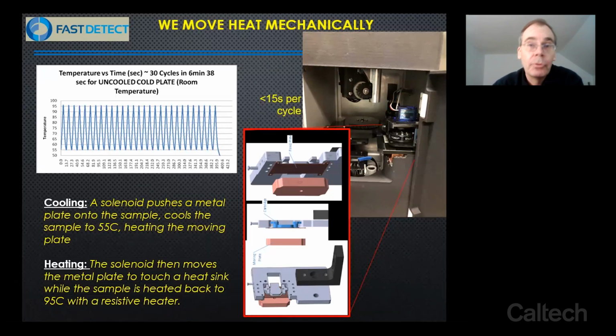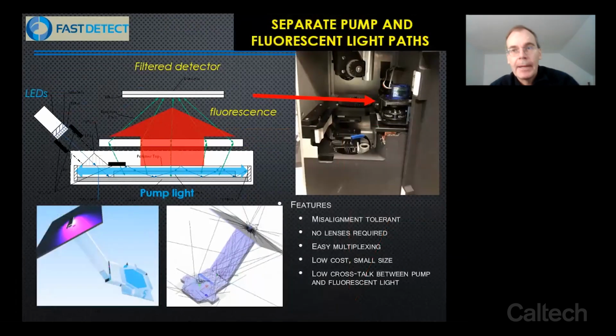And we can heat and cool with 15 seconds per cycle, which is relatively fast. That gives us the 10 to 15-minute amplification that we need. At the same time as amplifying, we also watch the fluorescence. We have four wavelengths that we're measuring at the same time, and that allows us to do the negative control as well as a number of different materials. We could look at, for example, COVID-19 as well as other respiratory diseases like the common flu.